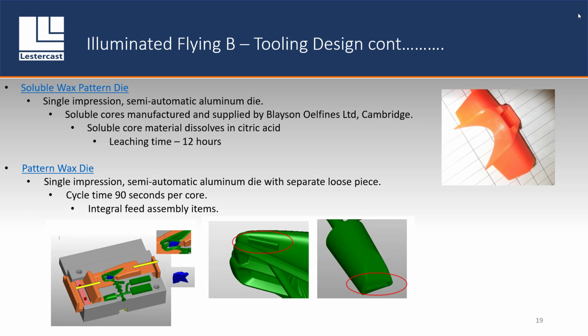It had to fit a soluble core, which obviously has its own contraction. It has to fit the ceramic core as well as an assembly, and then it all has to be surrounded by liquid wax. So you've got all this expansion of 3 or 4 different materials going on, and what you're hoping for is the ceramic core doesn't break during that pressure of the wax going in. This is before we've made a casting, by the way, actually making the wax itself.